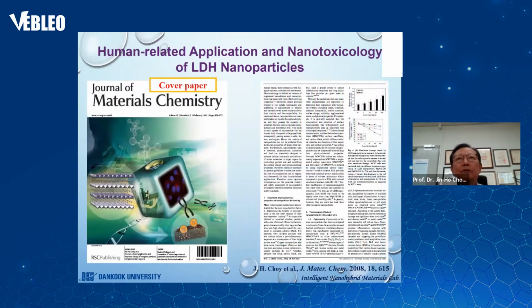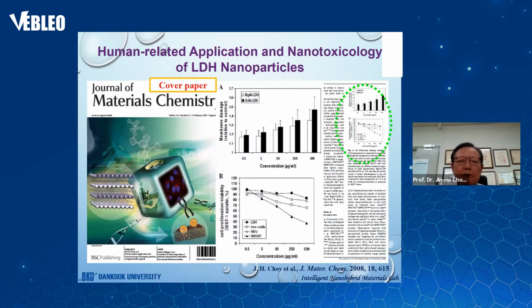So we also compared our inorganic particles with other inorganic particles such as iron oxide, SiO2, and single-walled carbon nanotube. And we found that out of 4 different inorganic particles, layered double hydroxide is the least toxic compared to the other inorganic nanoparticles.